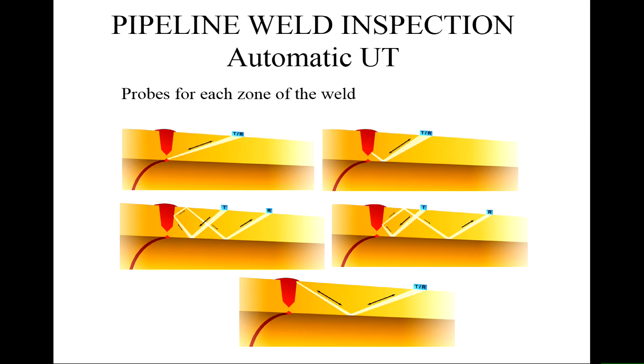So by designing the right transducer and receiver positions in an array of transducers and sensors, you can have signals that come from each part of the weld that can be separated, so that we don't get two sets of positions contributing to the same output. And that enables us therefore to measure particularly lack of fusion defects of different passes and do them all at the same time with one large array of sensors.